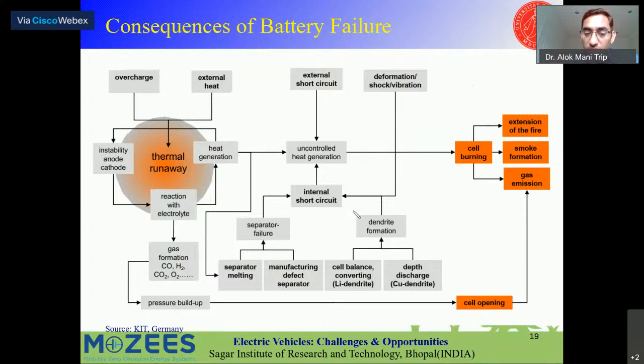Then there are issues coming from inside the cell, like cell balancing and converting. Lithium dendrite is coming. It will cause an internal short circuit because it's an inherent reaction inside the cell if you don't manage the cell in a good way. Then if depth of discharge goes very high, copper dendrite may come. And then if there is a manufacturing defect, like misalignment of the electrodes or loading, cracking, so many things are there. So the separator gets failed, and then what could happen? The cathode and anode can touch.